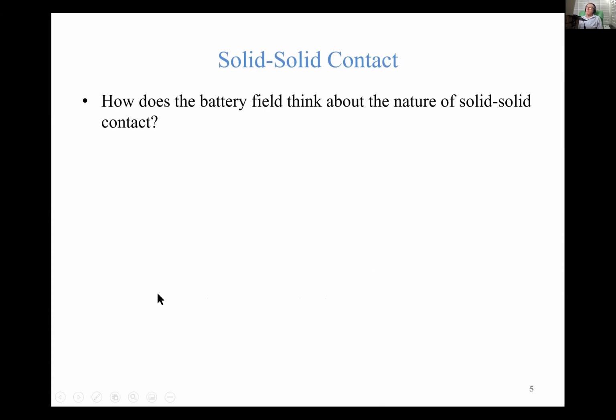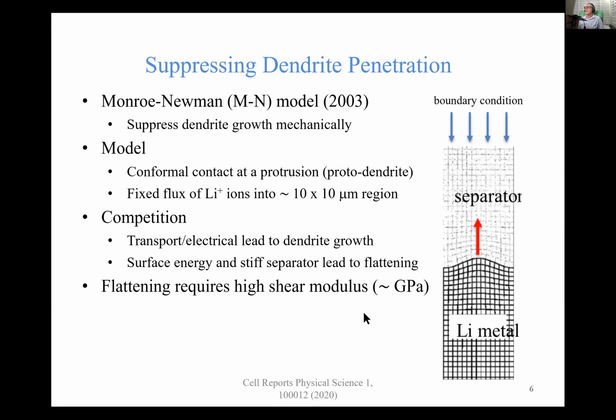So let's start with how do we deal with the interfacial resistance between a solid electrolyte and lithium metal. So let's start with the question, how does the battery field think about the nature of solid-solid contact? And it comes back to a paper by Monroe and Newman in 2003, where they said the way to prevent dendrites is to suppress them mechanically. And this is a figure from their paper. You've got lithium metal. In their paper, this is a solid polymer separator. And there's a boundary condition coming in from above where lithium ions enter this fixed volume, which might be 10 by 10 microns. And the lithium metal starts off with some random protrusion or protodendrite.